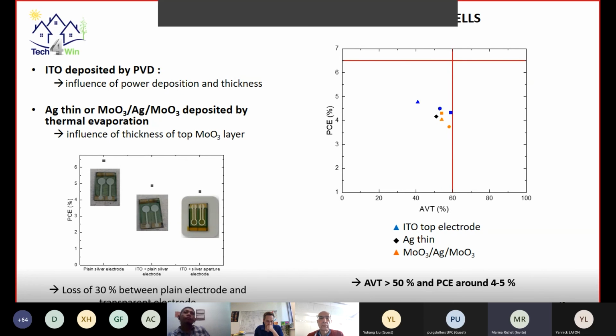So, in the first graph, we can see we have a loss of 30% of efficiency between the solar cell with the plain silver electrode compared to the transparent electrode. And if we detail the results with the different top electrodes, so ITO, silver, or two-layer electrode, we can see that the best performance is obtained with ITO, with performance up to 4.8%.